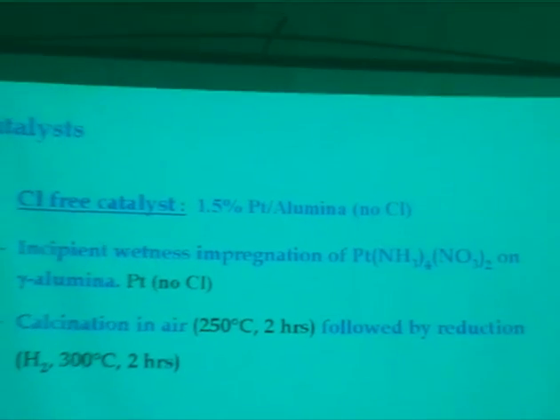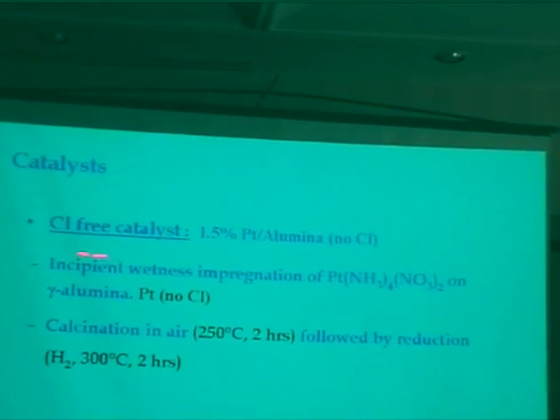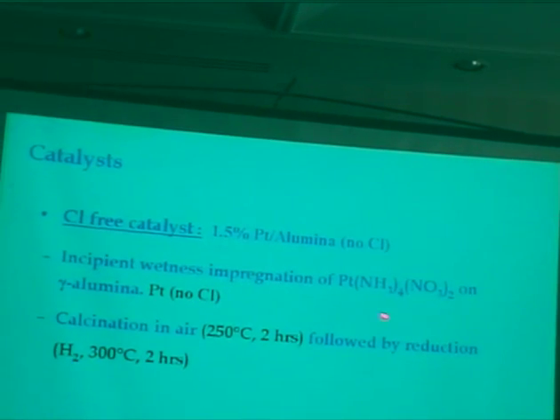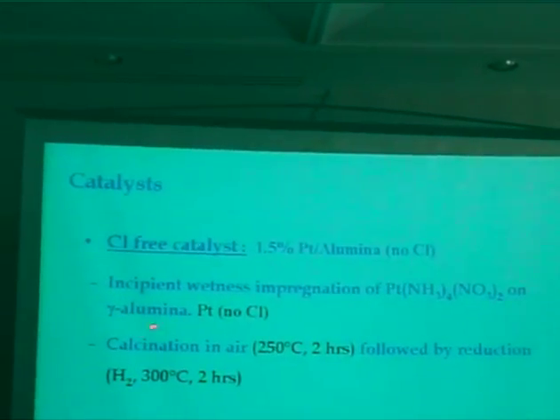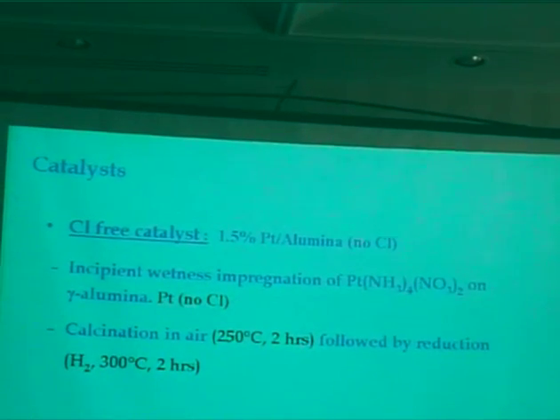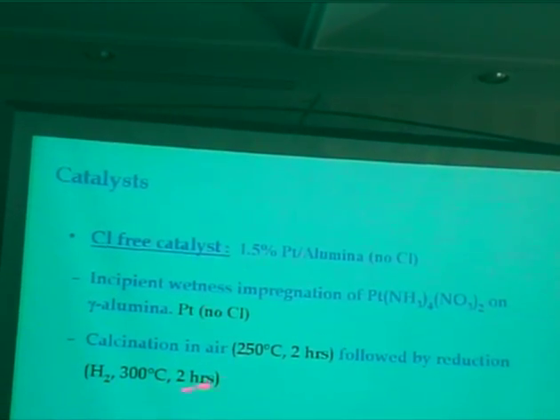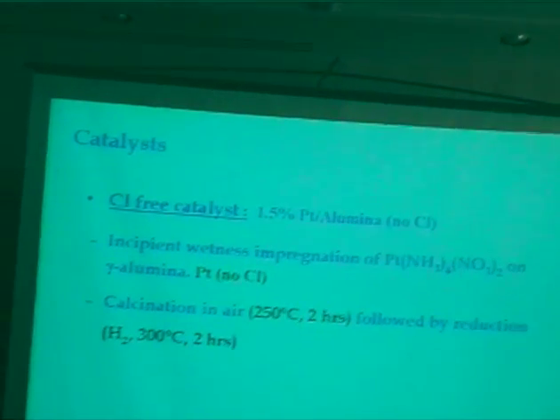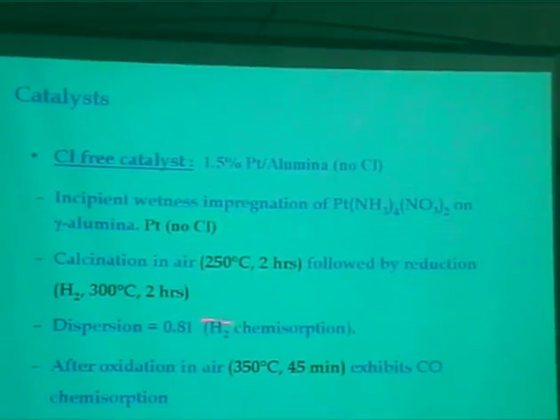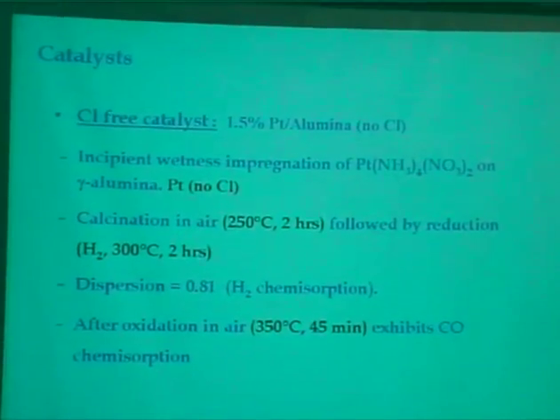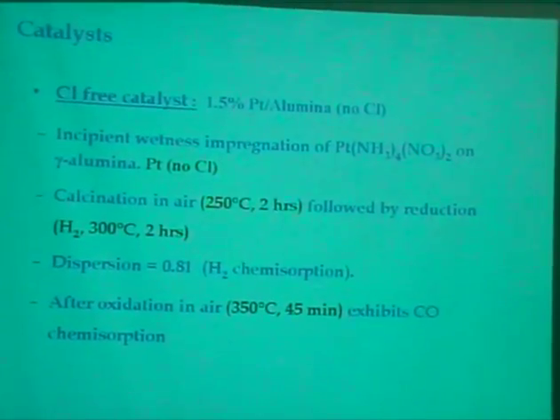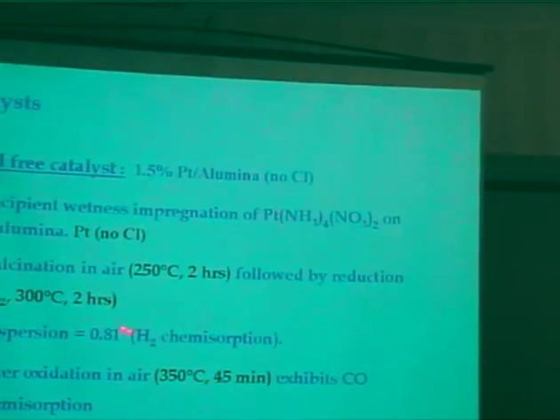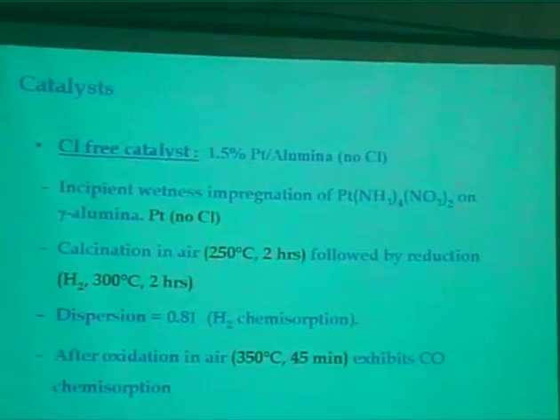So we're going to use two catalysts, one that has no chlorine: incipient wetness impregnation with platinum ammonium nitrate on alumina, and we're going to call this platinum with no chlorine. We calcine this at 250 and then reduce in order to do chemisorption. If you do this with this particular precursor, you get pretty high dispersion. This is one of the requirements if you're going to do XAFS and relate the results to surface concentration. This was then oxidized in air before reaction, so the conditions are similar to those that we use in reaction, and as we'll show, this is very significant. And when we do this after oxidation, we can see CO chemisorption as well.